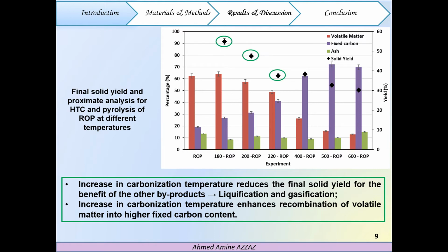suggest that the carbonization of raw olive pomace at relatively low temperatures, in the case of hydrothermal carbonization, led to higher solid yields. In fact, the final carbonization yield of hydrochar was estimated between 55% and 38% for treatments between 180 and 200 degrees Celsius respectively. This could be attributed to the low effect of heat and the presence of water in the form of liquid and vapor that reduces the possible solid losses in the form of volatile matter. On the other hand, pyrolysis of the raw olive pomace at high temperatures stimulated the elimination of volatile matter and the degradation of the lignocellulosic matrix, which resulted in lower solid yields between 38% and 30% for pyrolysis temperatures between 400 degrees Celsius and 600 degrees Celsius respectively.